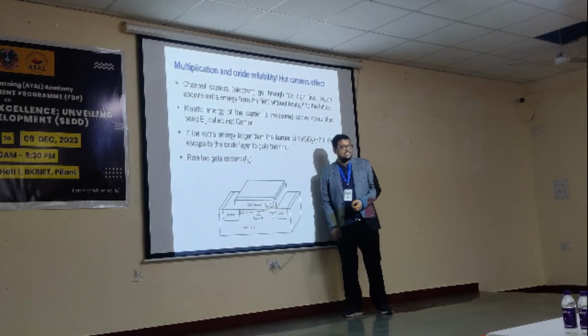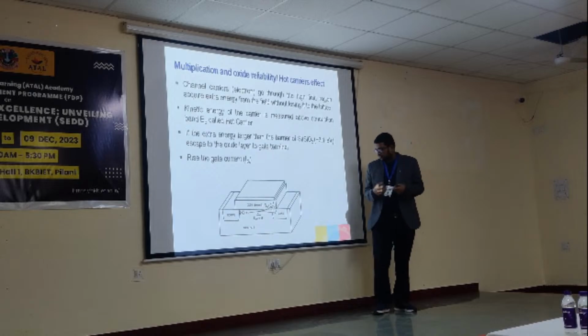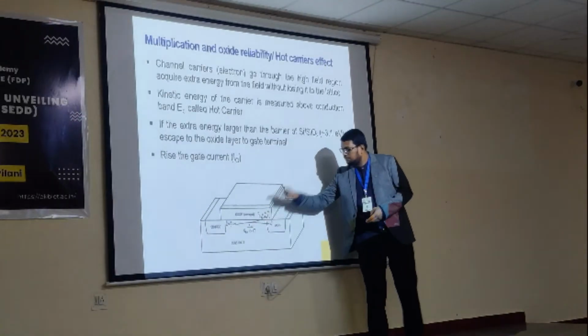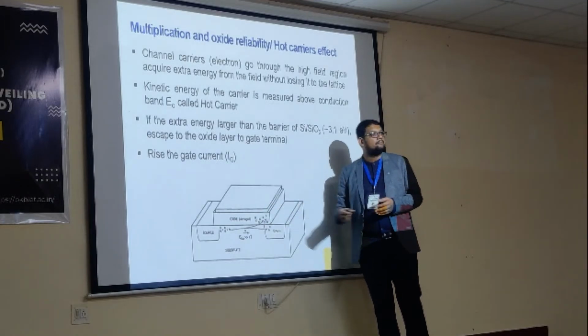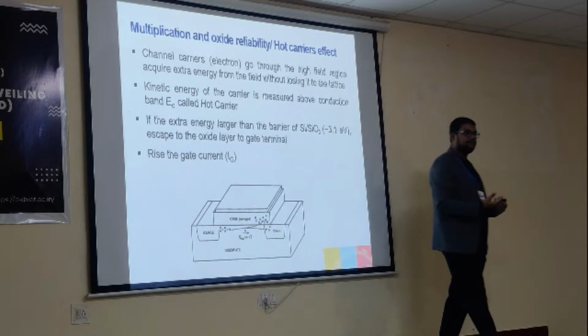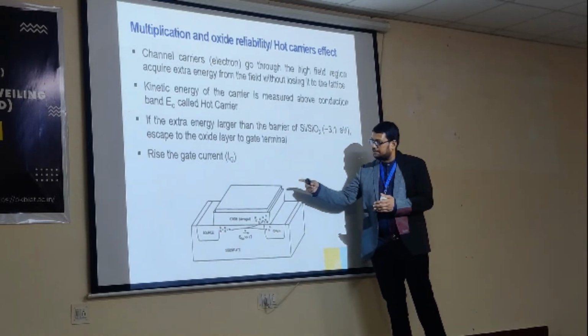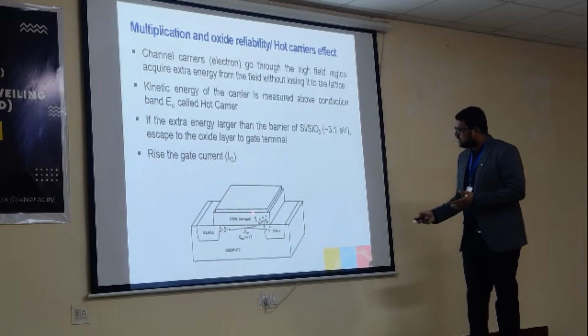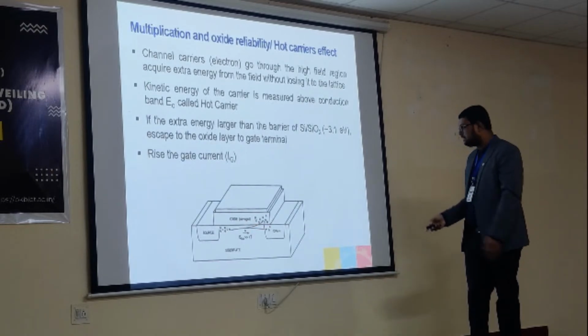But when the channels are very short, the electric field is very high, and these carriers achieve very high kinetic energy, high half mv square, so they can overcome this 3.1 electron volt and reach the oxide. When electrons enter the oxide, it is not a reversible process. They do not revert back to the channel. They stay there, and the oxide quality degrades. The oxide becomes poor, and if this situation continues, the oxide performance will be poor and after some time it will break down. So oxide breakdown is possible. These energized carriers, due to the high electric field from the short channel effects, are called hot carriers because they are highly energized.